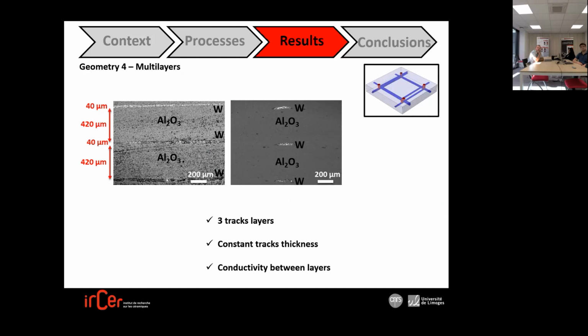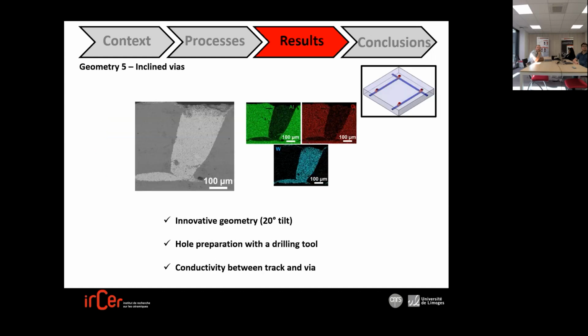Here you can see a multi-layer part with 3 tungsten tracks between alumina substrate of about 420 and 40 microns. We can see 3 layers with constant track thickness and conductivity between each layer using vertical vias. Here we try to make inclined vias with 20-degree tilt. The whole preparation has been made with a drilling tool, and then the via has been filled. And we can say at the end, after heat treatment, that we've got a good conductivity between tracks and vias.